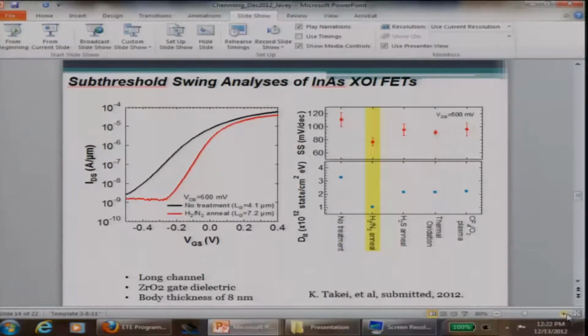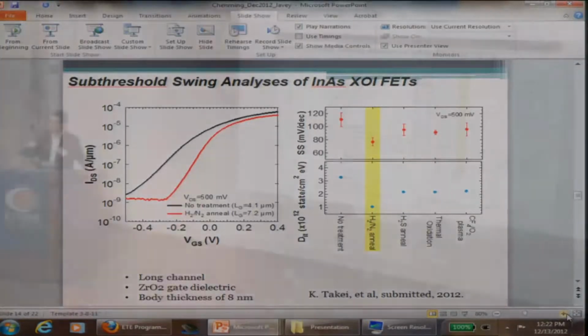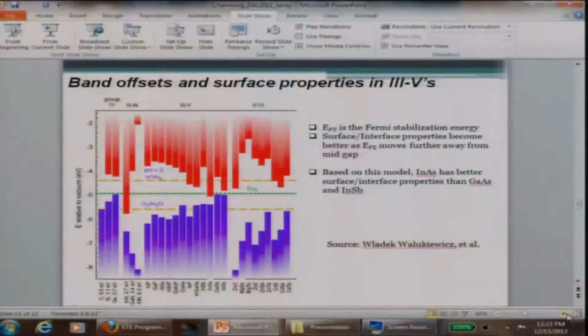60 millivolt per decade. Now, these subthreshold swings are very close to untransferred indium arsenide or InGaAs quantum well structures that people have grown on III-V wafers. So that means that our transfer process doesn't degrade the surface properties. We can still get pretty good transistor properties even after the transfer process. So the question is, why, and what's so magical about indium arsenide?